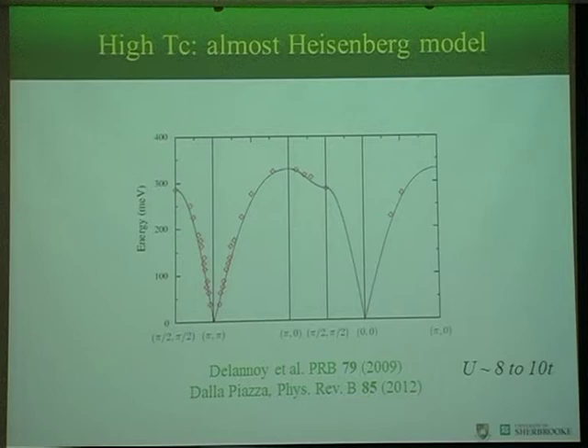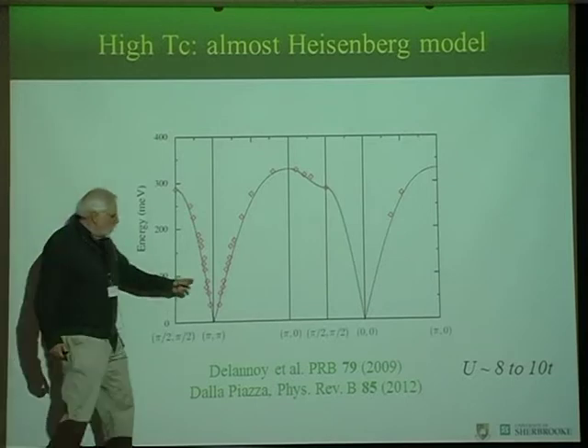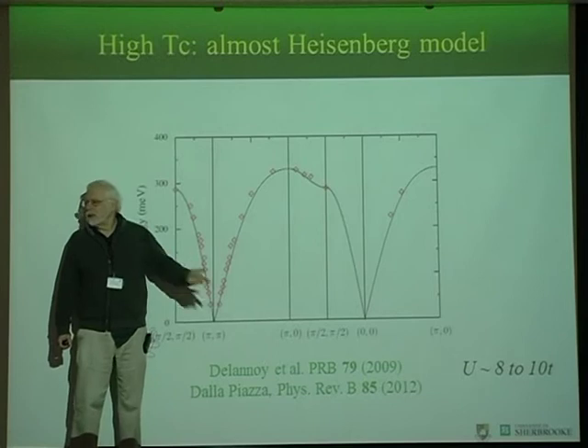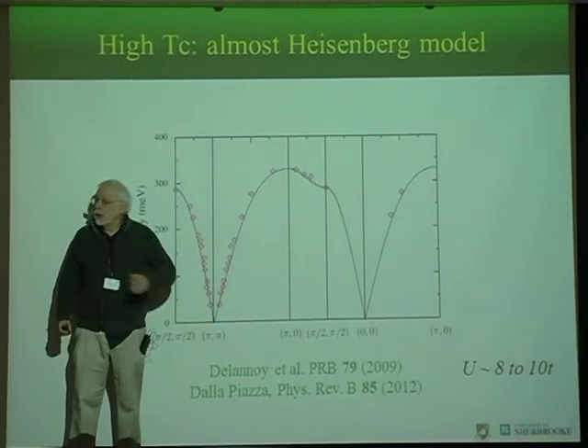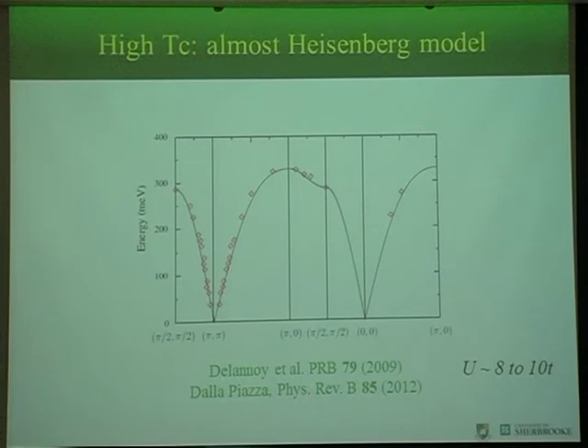The ring exchange value that you calculate, is that consistent? For example, you can get the U from two things, right? You can get it from the slope, or you can get it from that. No, unfortunately, you cannot get U from the slope here. What you can get is only 4T square over U. So you need an independent estimate of T. Oh, right. Okay, so you can take it from band structure, but if you want to stay within purely RIXS experiment, then you need to fit the whole spectrum to extract T and U independently. I see. And in fact, T prime and T double prime.